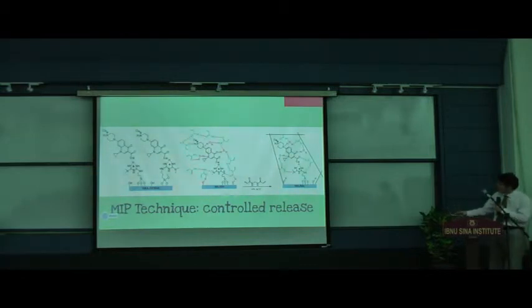So we also applied MIP technique to have controlled release. In MIP technique, you use polymer to cover the drug or medicine which is attached to the surface at a special pH, and at another pH you can easily remove the polymer and control release. This research paper is still in progress.